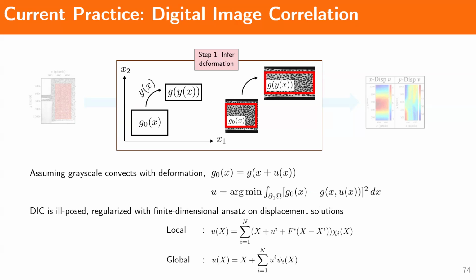And the DIC problem really is, assuming your grayscale or your speckle pattern convects with the deformation, we are trying to minimize the difference between the deformed speckles with respect to the undeformed speckles over all possible solution fields U here. So U is our displacement field, and we're really trying to maximize the correlation between the two eventually, right? Now, this is a typical classical optimal transport problem, and it is well known here that the minimizers may not exist, or if you have a minimizing sequence, it may not converge. So DIC here is an ill-posed problem because of these reasons.